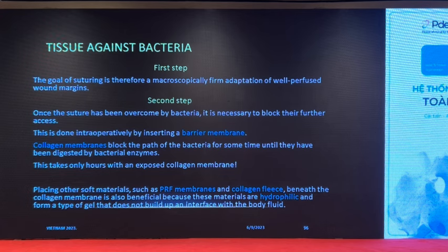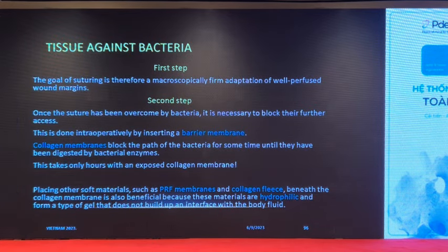Placing other soft materials, PRF membranes and collagen fleece, for example, beneath the collagen membrane is also beneficial because these materials are hydrophilic and form a type of gel that does not build up an interface with the body fluid.